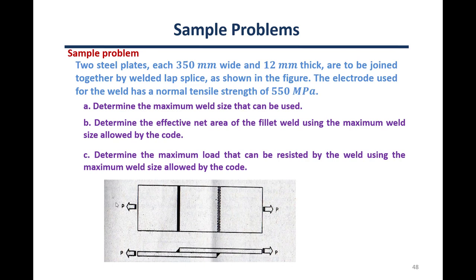We have two plates, 350 mm wide and 12 mm thick, to be joined together and welded as a lap splice as shown in the figure. So makikita yan, parang ganyan. The electrode used for the weld has a nominal tensile strength of 550. We have to determine the maximum weld size, the effective net area using the maximum weld size allowable by the code, and the maximum load that can be resisted by the weld using the maximum weld size allowable in the code, of course.